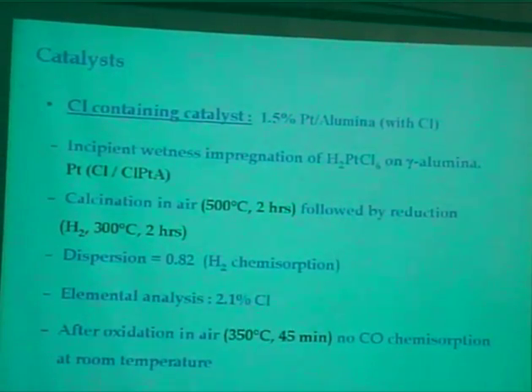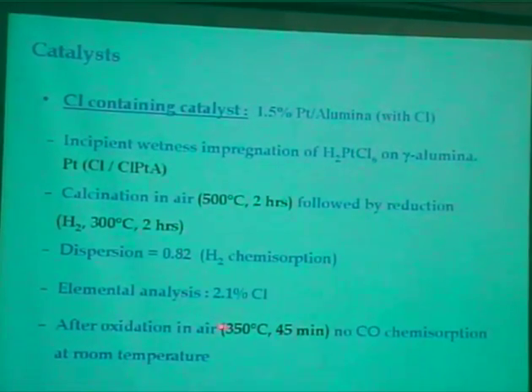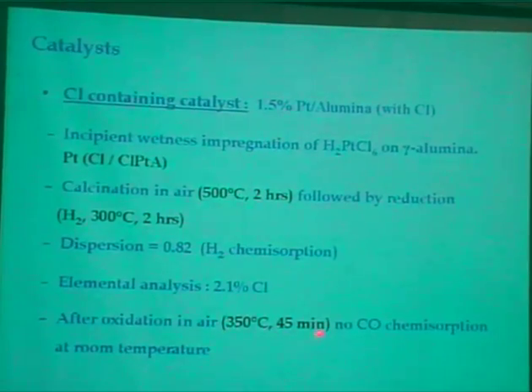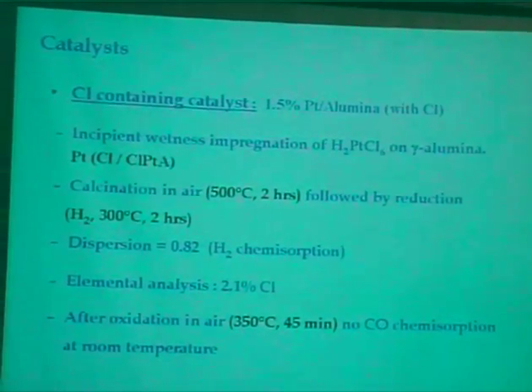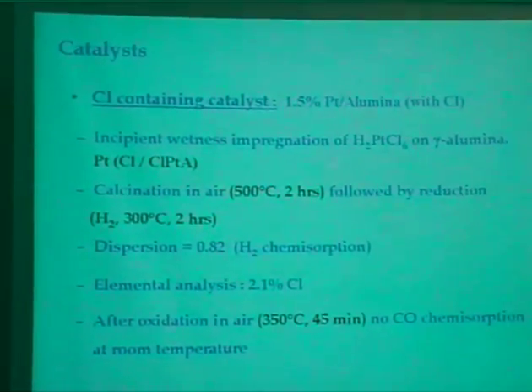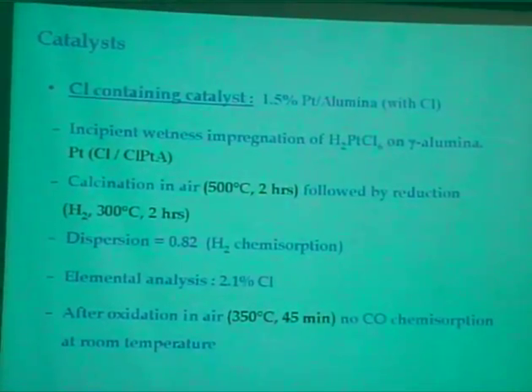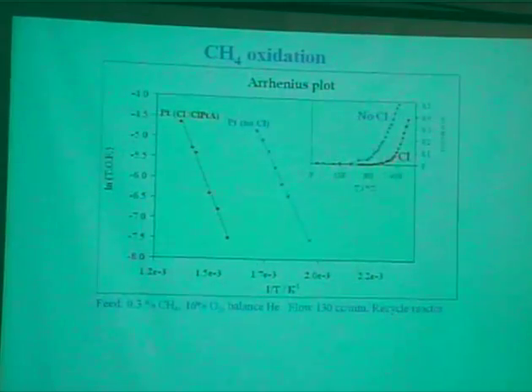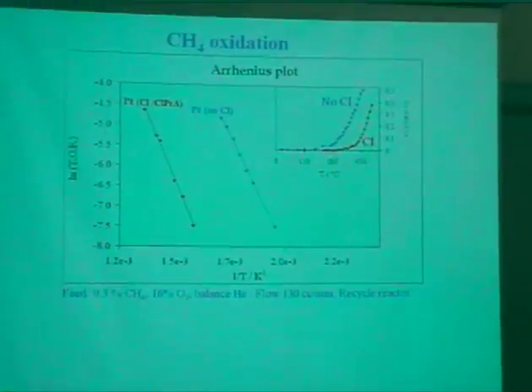Elemental analysis indicates that we do have chlorine, and again we do the oxidation, and we see no CO chemisorption at room temperature. That doesn't mean that there's no CO chemisorption at reaction temperature. Okay, so how do we obtain the data?